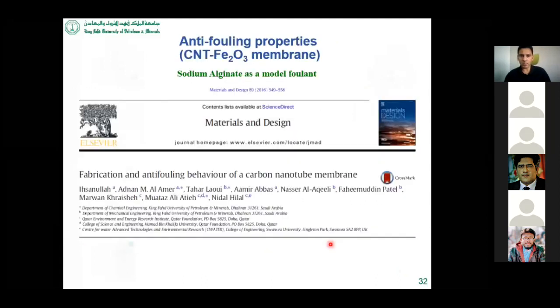So if someone is interested to study more in this area, there is another paper. We studied the anti-fouling characteristic of the iron oxide modified carbon nanotube membrane. So here I want to highlight again that the entire membrane is made of carbon nanotube, and only a smaller loading of the iron oxide was used. So we found that this membrane also has excellent anti-fouling potential. We used sodium alginate as a model foulant. So you can study this paper in detail if you are interested.